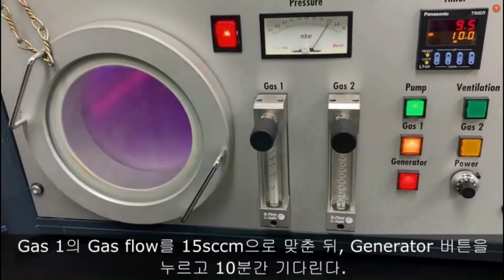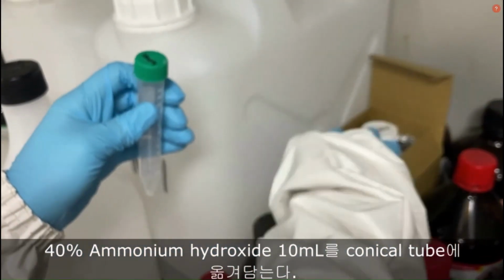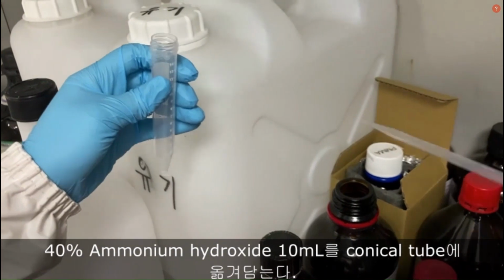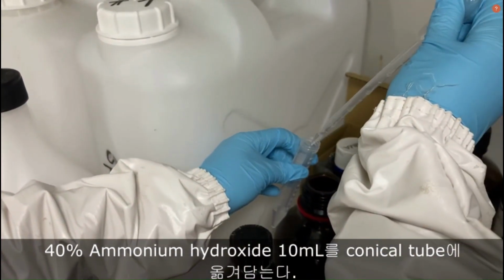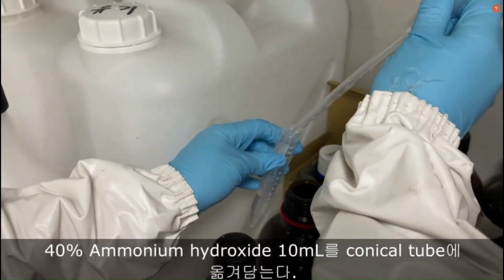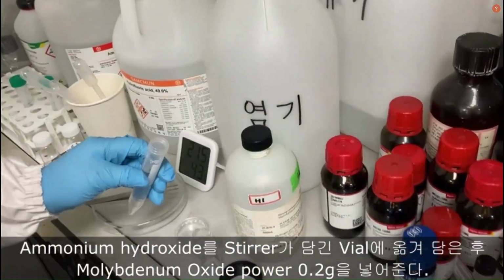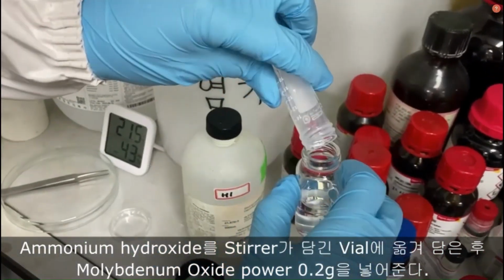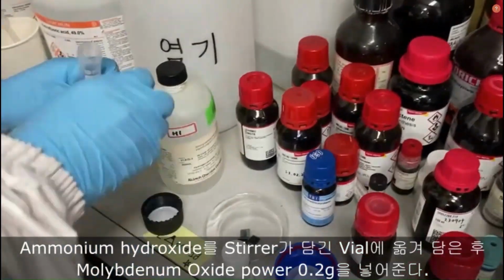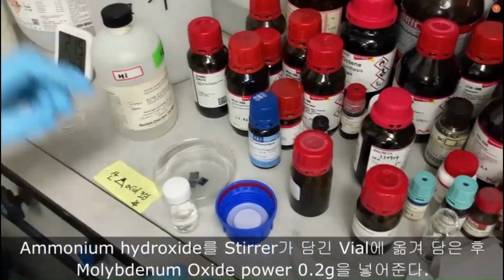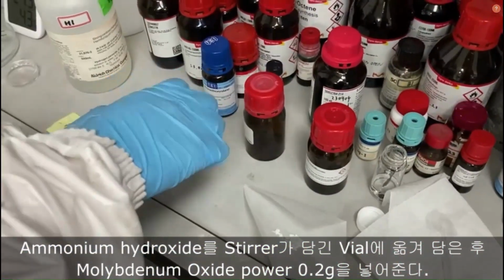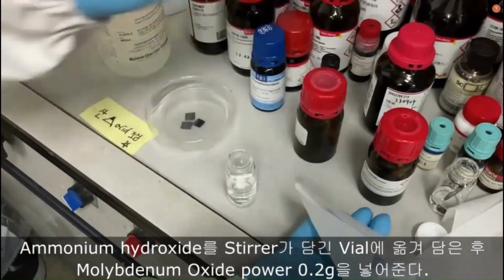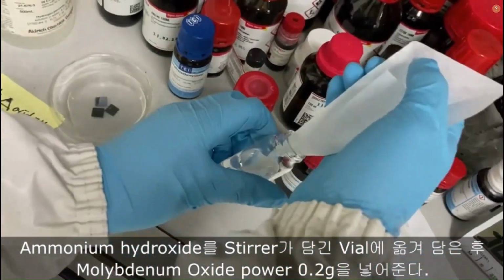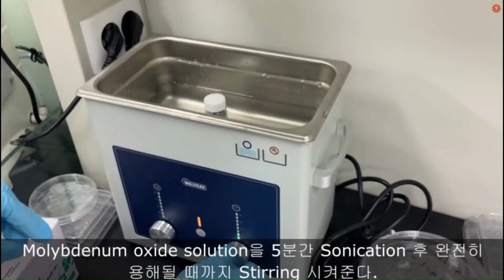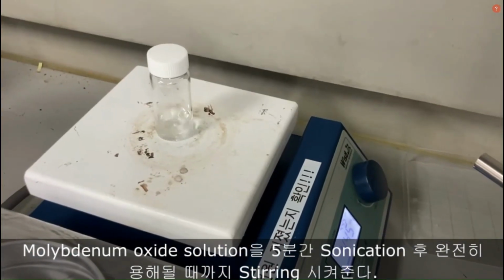While waiting for plasma treatment, let's prepare the molybdenum trioxide solution. To make the molybdenum trioxide solution, mix 0.2 grams of molybdenum trioxide powder with 10 ml of 40% ammonium hydroxide solution. Sonicate the solution for 5 minutes, then stir until the powder is completely dissolved.